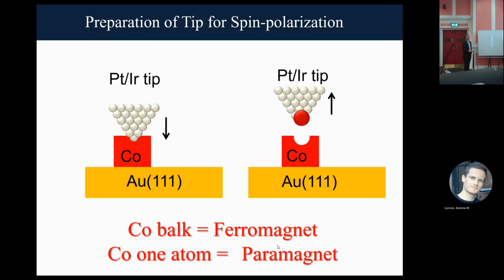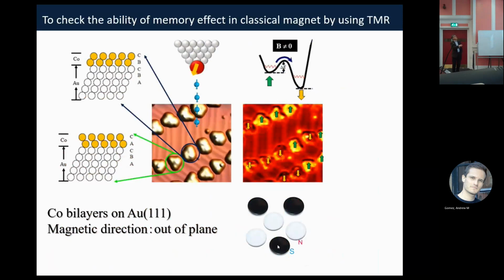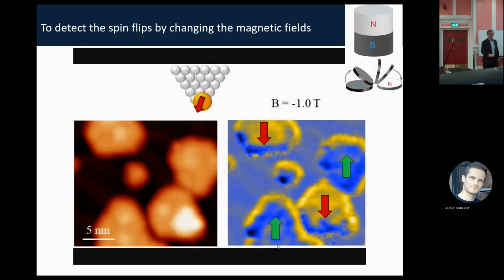So this is a result to check the ability of memory effect in a classical magnet. This is a cobalt island, classical magnet. You can see bright spots, spins up. Division 1, 1, 1, 1. This is a dark color, down. 1, 1, 1, 0, 0, 0, 0, 1, 0, 1. We put the information 1, 0 in the bulk magnet, like an oscillator. Black, down spin; white, up spin, like an oscillator. So I show the movie.